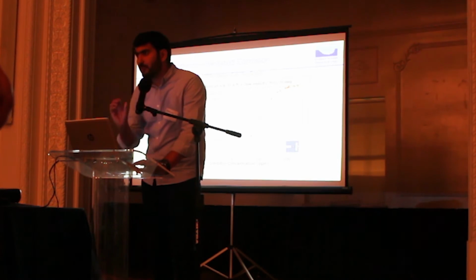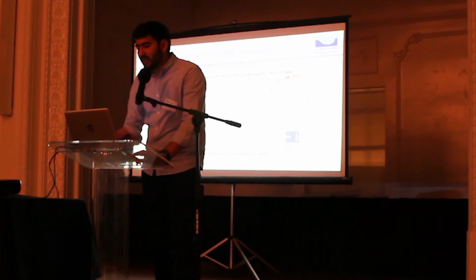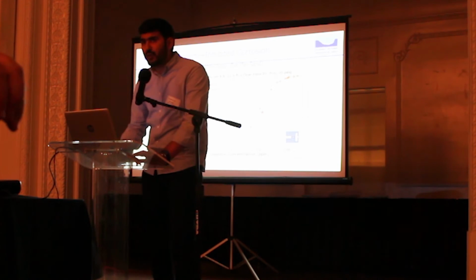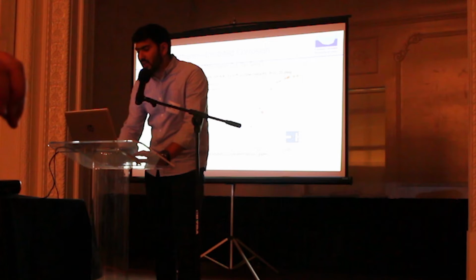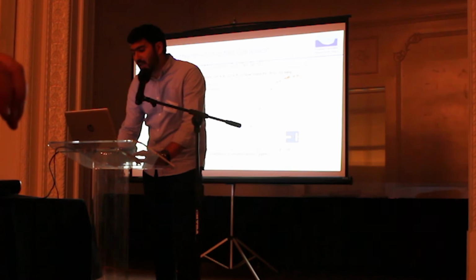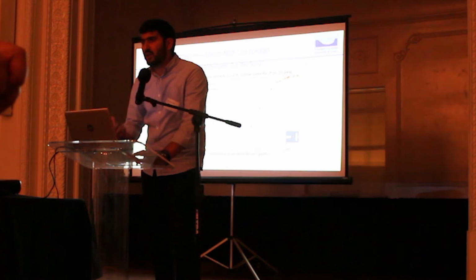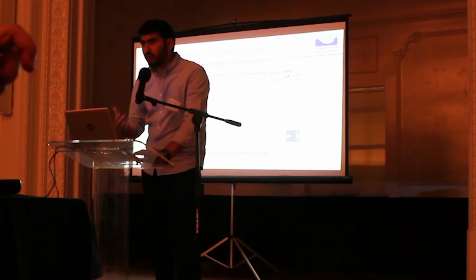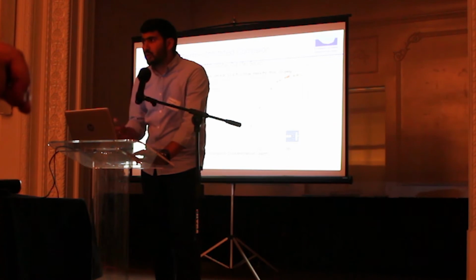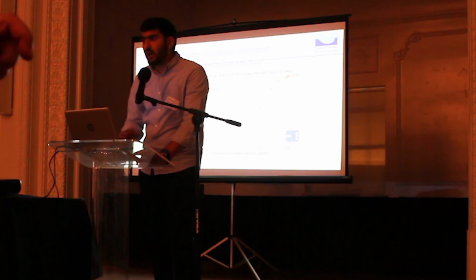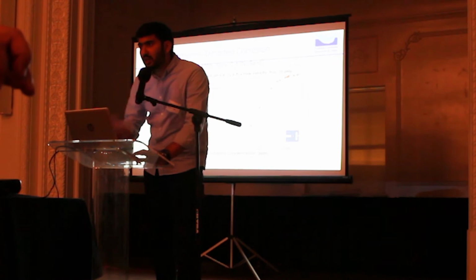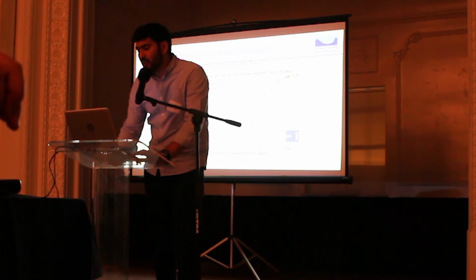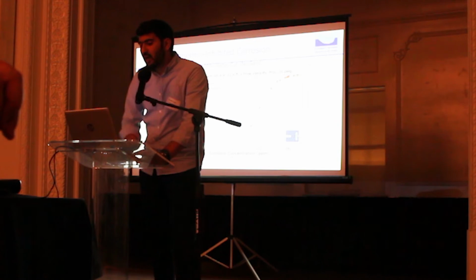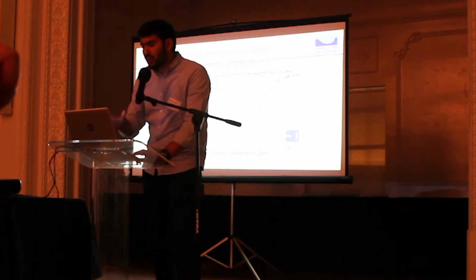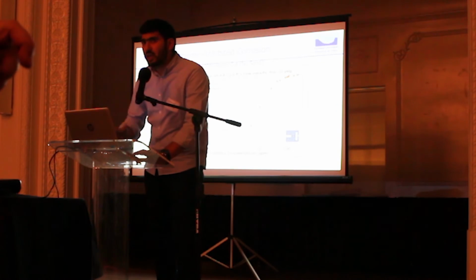The orange circle data points represent inhibited corrosion experimental data, and the green line represents the Frumkin isotherm fit to these inhibited corrosion data. As we can see here, one axis represents the inhibitor concentration in ppm, and the other axis represents the surface coverage by the inhibitor. So what does zero mean? Zero means no coverage, and corrosion rate is relatively high, and 1 means complete coverage by the inhibitor, and corrosion rate is getting low. As we can see here, there is an exponential relationship between the inhibitor concentration and the surface coverage by the inhibitor. So this was data for inhibited corrosion in absence of solid particles.